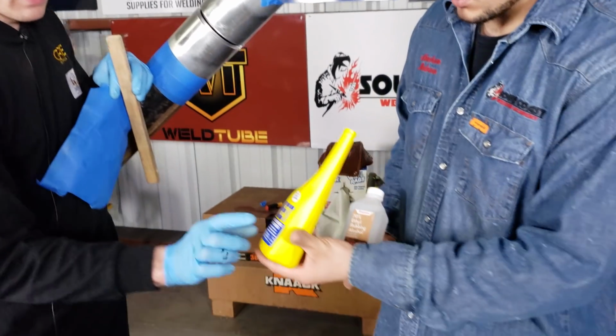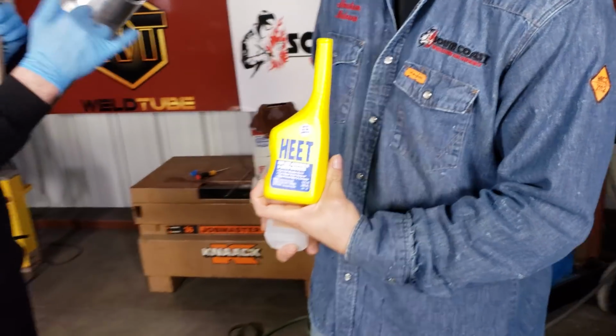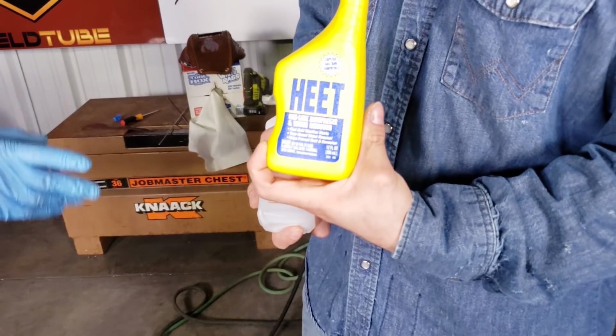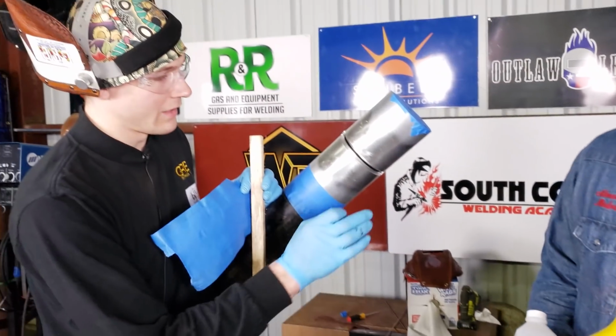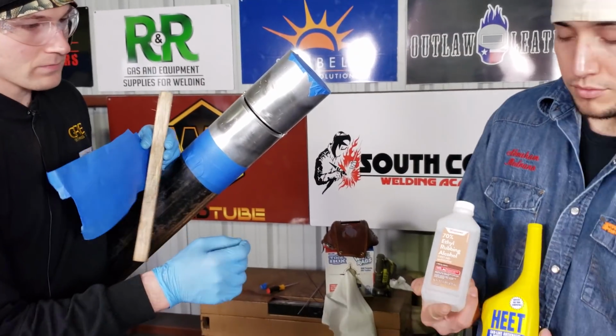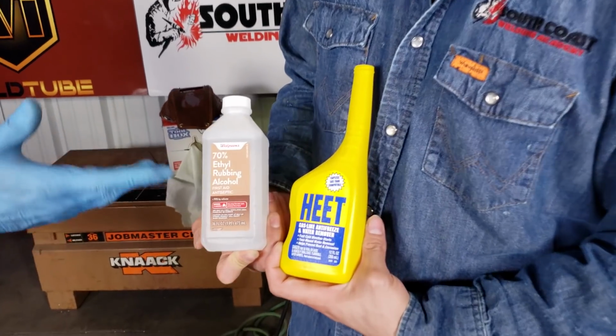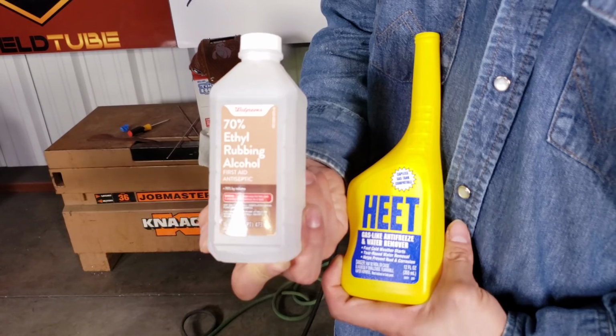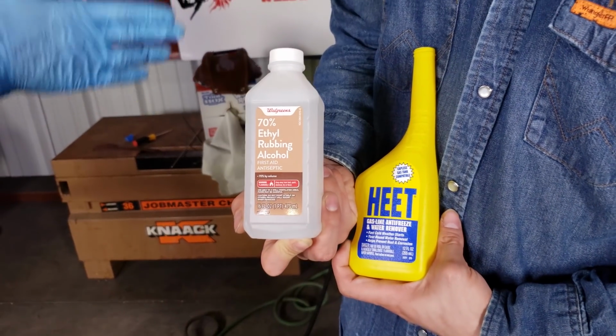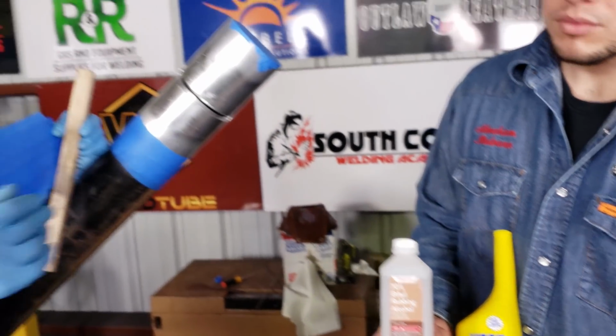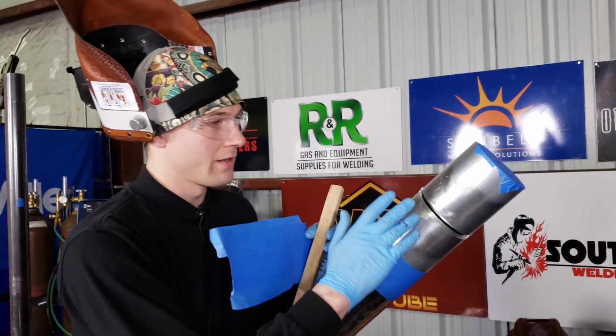Typically, you clean the material, the filler metal, and the pipe and everything with acetone and antifreeze. But when it comes to tape residue, I found that the easiest and most efficient way to remove it seems to be rubbing alcohol, even though it is flammable. Rubbing alcohol does remove tape residue from the heat-affected zone, and that is part of prepping the area for welding.